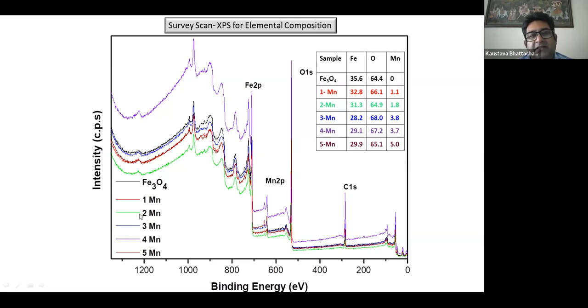So you can check, initially these peaks we are seeing here are basically Auger electron peaks, AES peaks as we say, and these peaks like Fe2p, this is the peak for iron. As I was telling, XPS doesn't see any material as a compound. It always sees it in the form of elements. So for Fe3O4, Fe3O4 will be somewhere here.